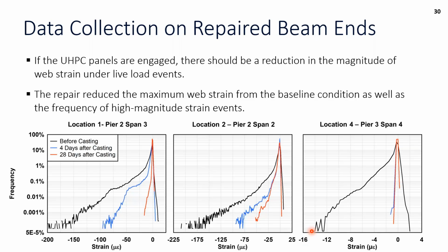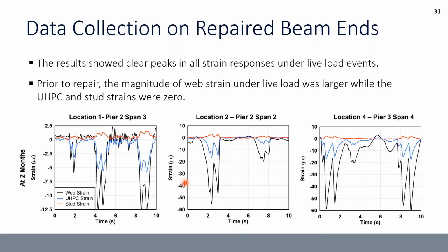And one of the other things that we were looking for is that we wanted to just see a correlation between our strain measurements. So when we're getting a peak from a truck on the web, that we're also picking up that strain in both the UHPC and the studs. And we saw that on all ends as well.